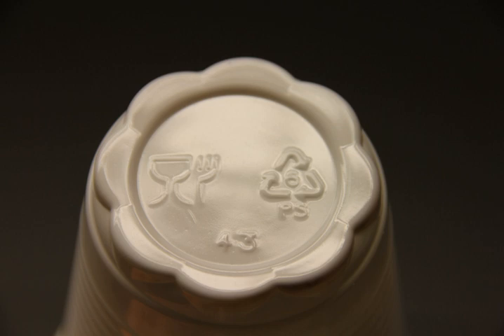Topic: Water absorption of polystyrene foams. Although it is a closed cell foam, both expanded and extruded polystyrene are not entirely waterproof or vaporproof. In expanded polystyrene, there are interstitial gaps between the expanded closed cell pellets that form an open network of channels between the bonded pellets, and this network of gaps can become filled with liquid water. If the water freezes into ice, it expands and can cause polystyrene pellets to break off from the foam.